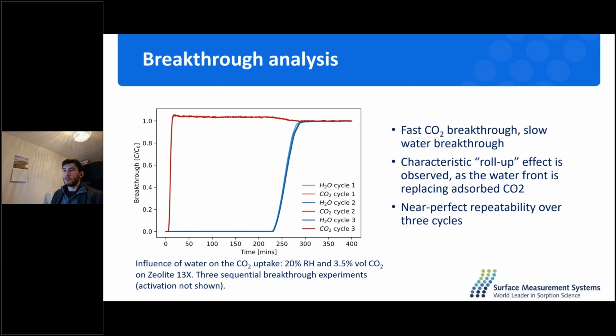So the way to approach this is through breakthrough analysis. With breakthrough analysis, you can monitor concentrations independently at the outlet. So you can put in a mixture of CO2 and water, which is exactly what this breakthrough curve shows, and record the outlet concentrations of each independently. By integrating the two curves, one can obtain actual multi-component uptakes for each of these two components.